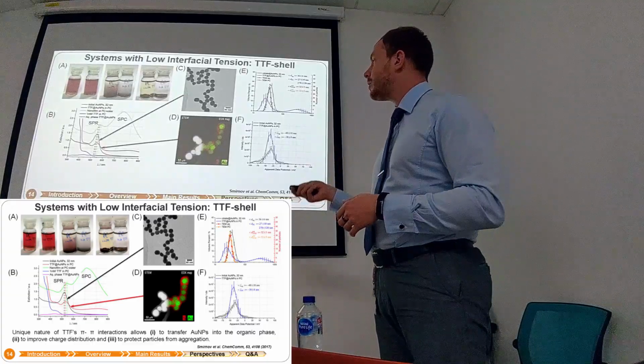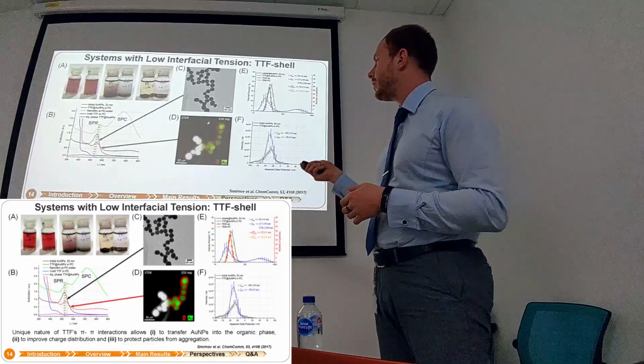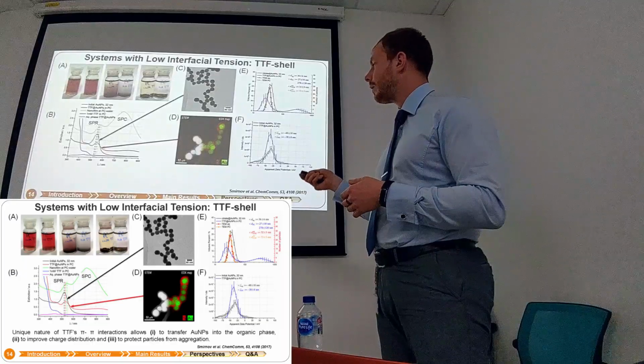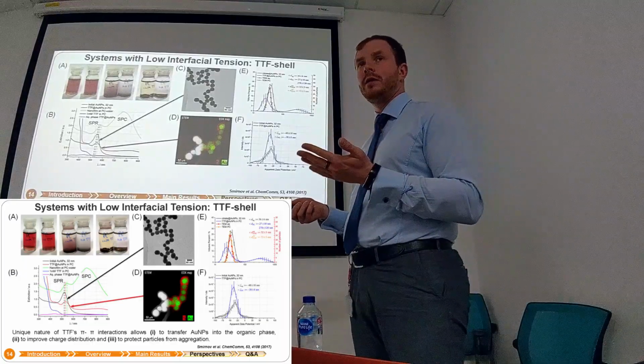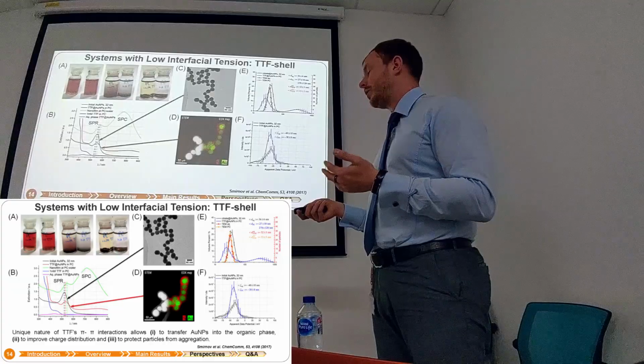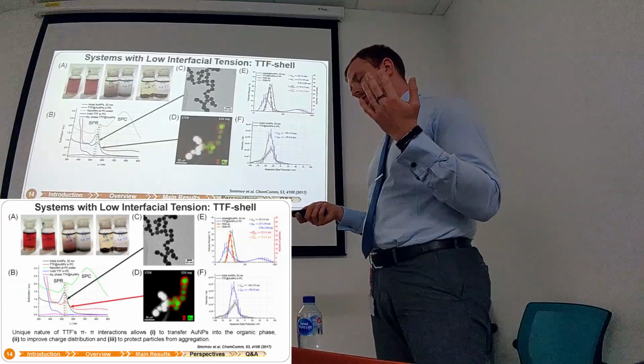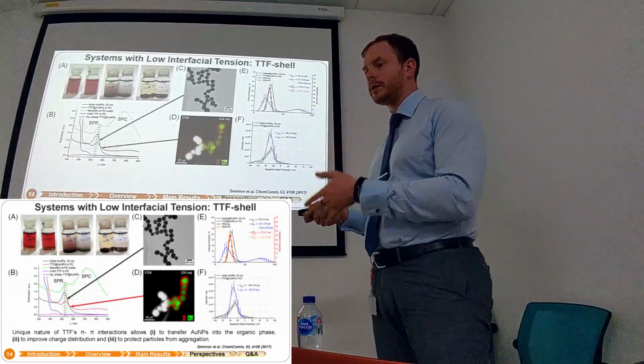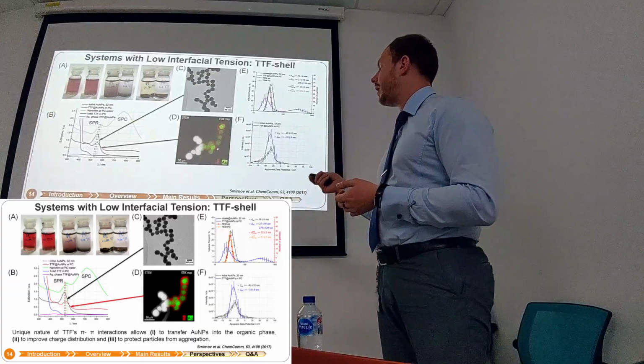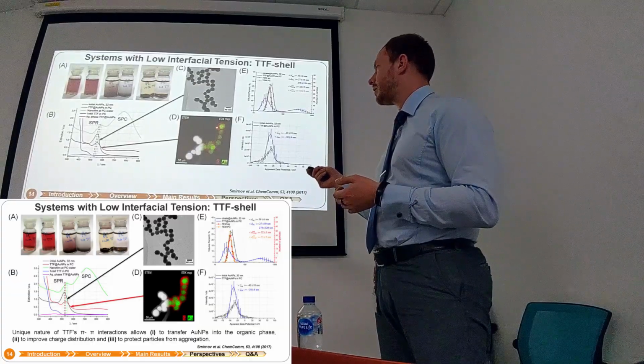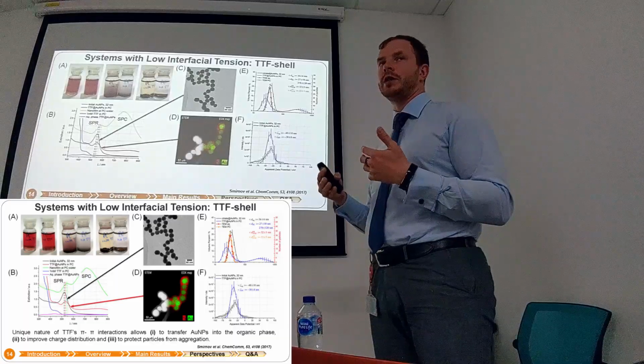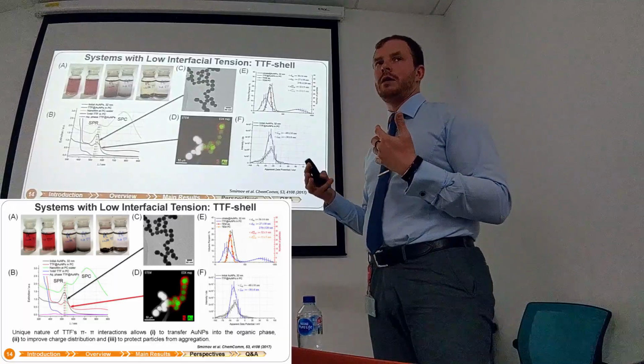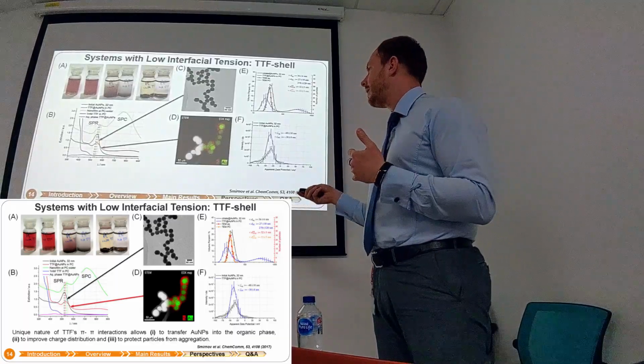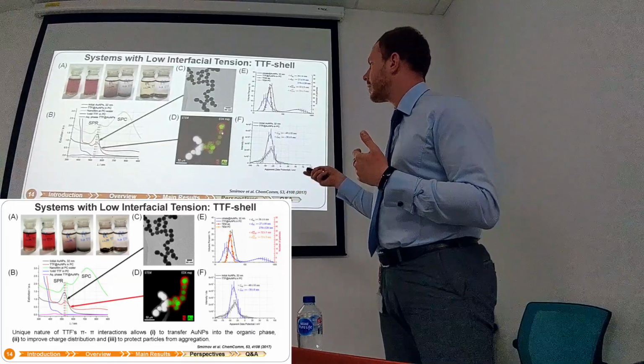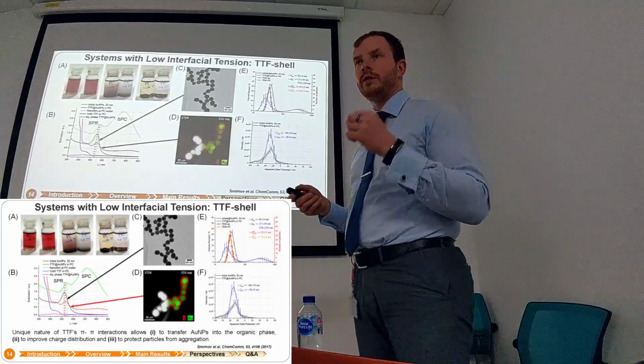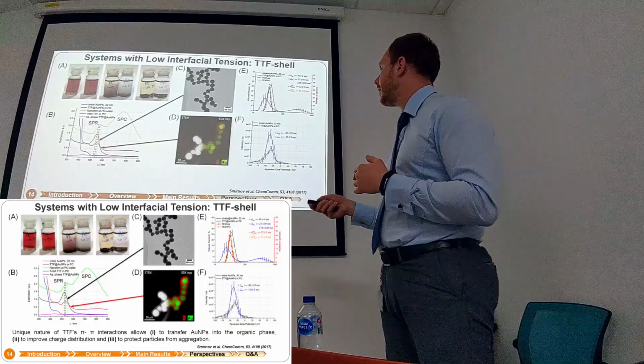Again, some pictures to show. For example, we did EDX mapping in STEM mode, so in scanning transmission electron microscopy mode, where we clearly show that nanoparticles are separated from each other by roughly 5 nanometer thickness of the film of TTF.